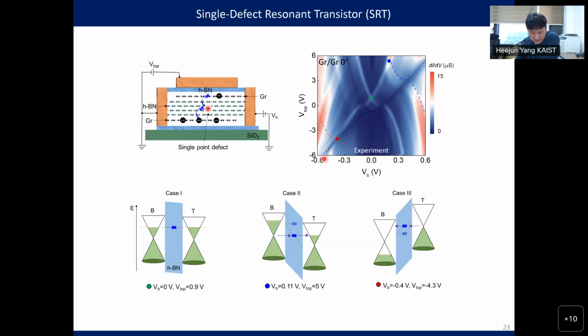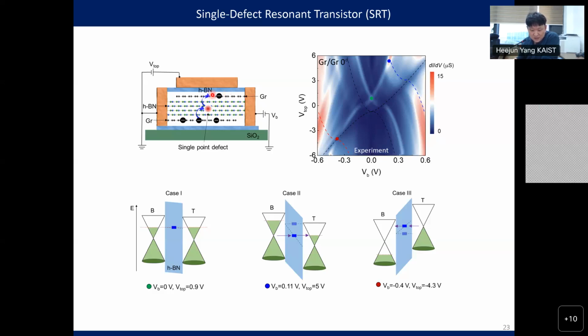And what about this bright line? Let's follow this bright line with positive slope. In this positive slope, we are increasing VB. Increasing VB means in this parallel capacitor, we are accumulating holes. But if we increase the top gating bias here, we are accumulating electrons. So if we follow the line, somehow we have compensation. We are accumulating holes from the bias, and electrons from the top gating. We have charge compensation. That's why we have this positive slope and negative slope from the bottom graphene.